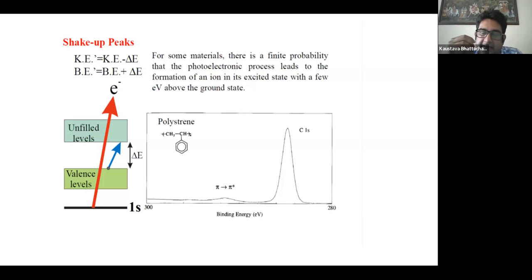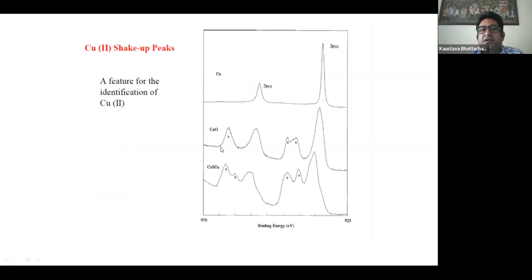So that can lead to the energy being enhanced. That is, that coupling can lead to an enhanced energy, which we call a shake-up, or it can lower the energy a bit, which we call a shake-down. For example, as I was telling, if I check copper metal, it's clean, and I get the 2p 3/2 and 2p 1/2 peaks. But for copper oxide, the oxygen has some contribution or overlap with that particular 2p orbital of the copper metal. That leads to another one or two peaks, which we call either satellite peaks or shake-up peaks.